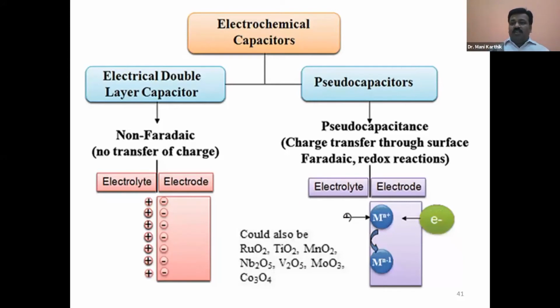So this is the major difference between the electrical double layer and the pseudocapacitor. Compared to the electrical double layer, pseudocapacitors give you a farad difference. You get more farads in the pseudocapacitor because of the pseudo behavior. That's the reason we get more capacitance than the electrical double layer, because that depends only on the porosity of the carbon. So there is no chemical reaction, only electrostatic interaction, whereas this has charge transfer interaction. So it's limited.